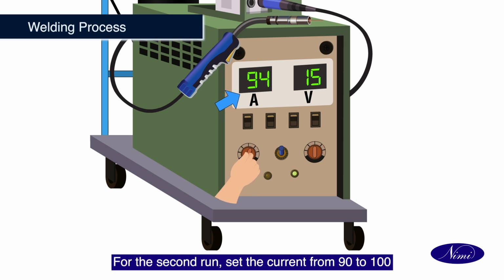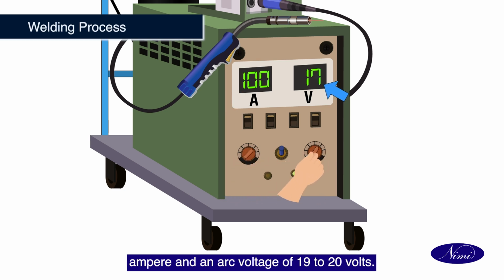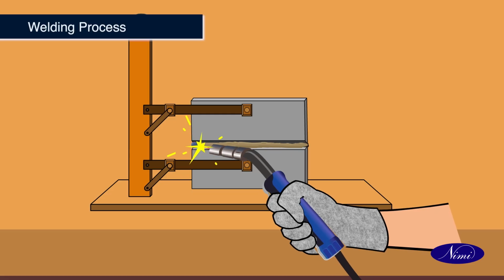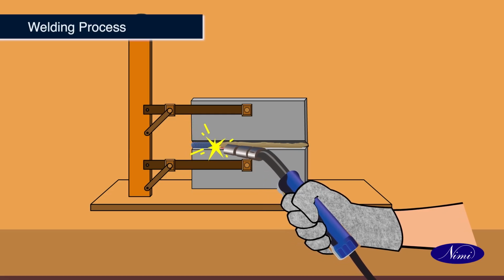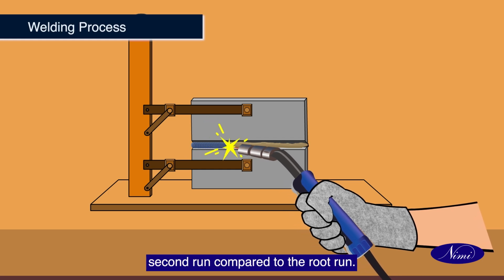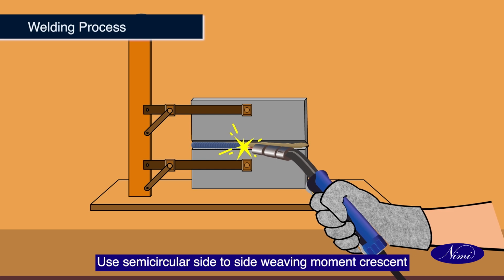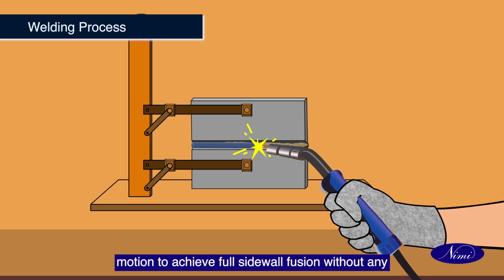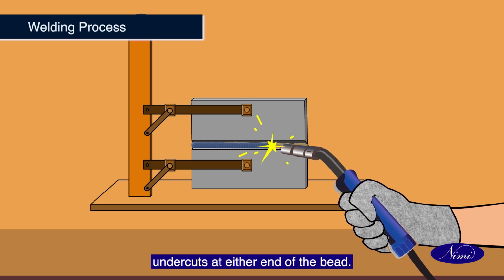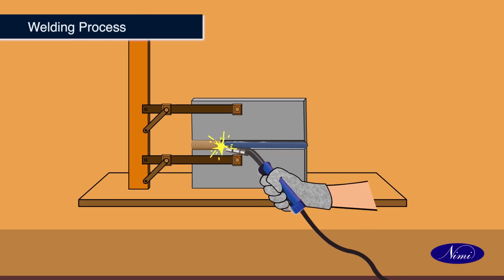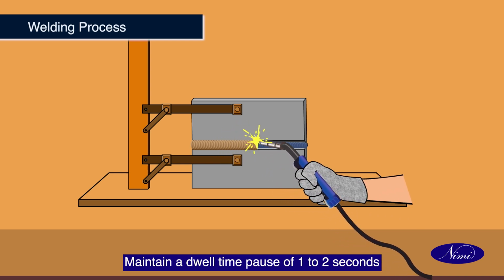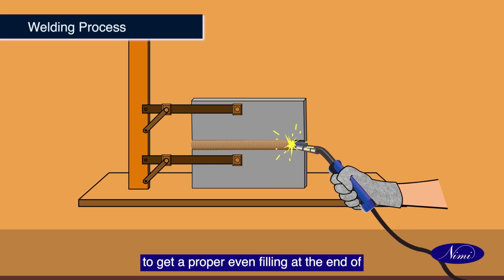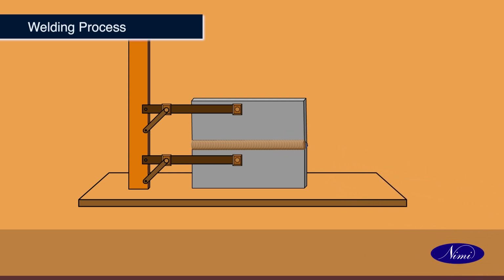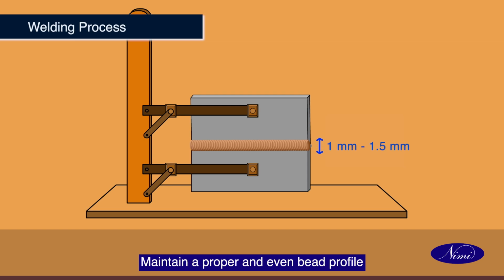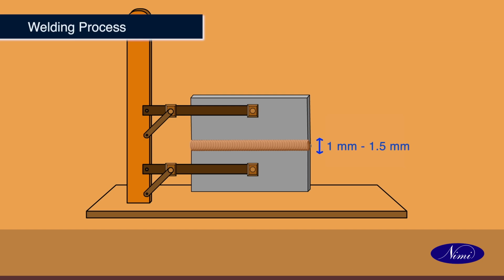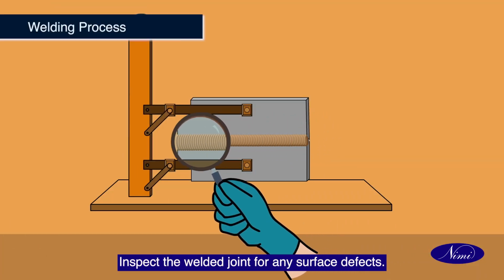For the second run, set the current from 90 to 100 ampere and an arc voltage of 19 to 20 volts. Maintain a slower travel speed for the second run compared to the root run. Use semicircular side-to-side weaving movement, crescent motion, to achieve full sidewall fusion without any undercuts at either end of the bead. Maintain a dwell time pause of 1 to 2 seconds to get a proper even filling at the end of the toes on either side of the bead. Maintain a proper and even bead profile and a reinforcement of 1 to 1.5 mm. Inspect the welded joint for any surface defects.